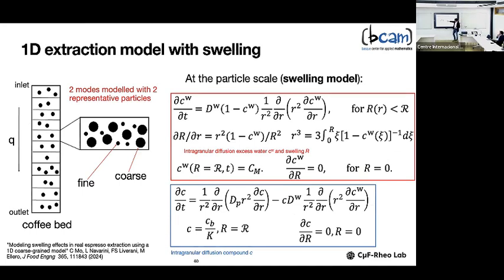The direction of the extraction is discretized by a certain number of layers. In each of these elements, you have one representative particle which represents the coarse, and one representative particle which represents the fines. And we resolve the swelling equation that I showed in the previous slides in these two particle sizes. The boundary condition that we use is that at the surface, the concentration we reach there will be equal to the concentration in the bulk divided by a partition parameter.